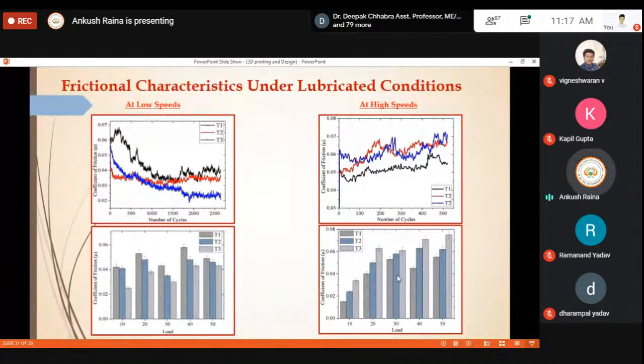Whereas if you talk about the high speeds, the reverse case is the texture T1 has shown the less coefficient of friction in comparison to the texture T3. The reason here again is quite logical, because if you increase the speed of testing, 100 rpm was the low speed and 500 rpm was the high speed. So what will happen? In that case, your oil will not be retained. Basically, we are talking about the lubricant retention capability. If the speed is less, the lubricant will be retained. If the speed is more, the lubricant will try to get away from the textures due to the